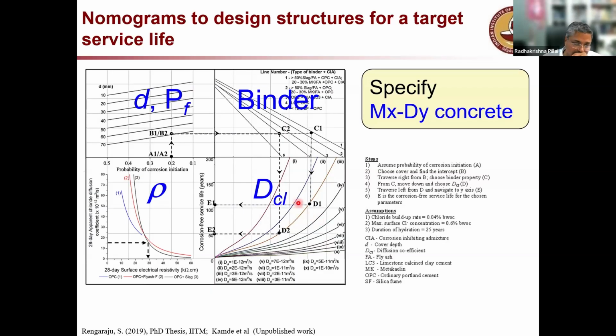So what do we do? We say that there is another test which is very simple to do and which we call the resistivity test. The Wenner 4-probe resistivity test. So we have come up with a relationship between the DCL and the resistivity. So here you can use this curve and say, okay, if my DCL is going to be the number 3, which is D3 into 10 to the power of minus 12, the corresponding resistivity will be something. Then I put that resistivity as the target.